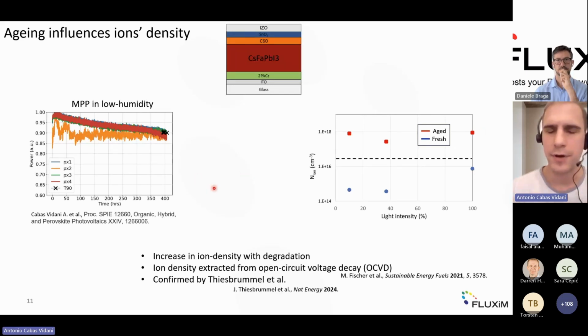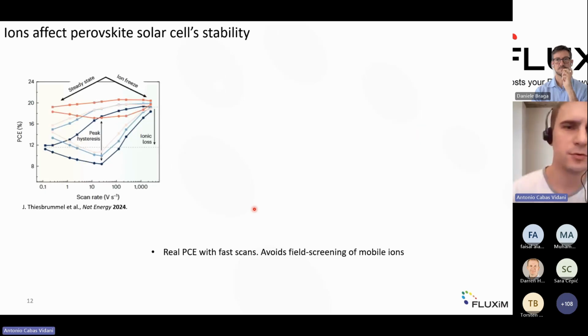This was a rather interesting observation, and interestingly it was also confirmed by Thiesbrummel et al., Thiesbrummel from Oxford PD. Now, the exact reasons behind it are unclear, but it is observed on multiple types of perovskites. And indeed, Thiesbrummel also quantified the effective impact of mobile ions on the PCE and on stability itself.